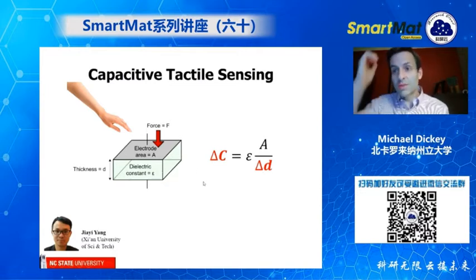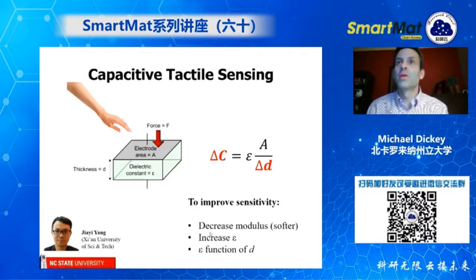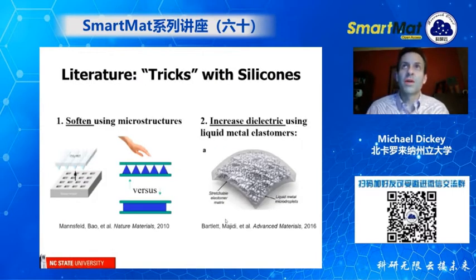So if you want to make your sensor very sensitive, there's a few ways to do it. One is to decrease the modulus, to make it very soft. Another is to increase the dielectric constant, or make the dielectric constant change as you press the material. So there's been some really great work in the literature, I call them tricks, with silicone. The first is to soften the silicone using microstructures. So instead of using a capacitor made of a slab of silicone, you actually use pyramids of silicone, and this is from the Bao group at Stanford. And so this results in greater sensitivity.